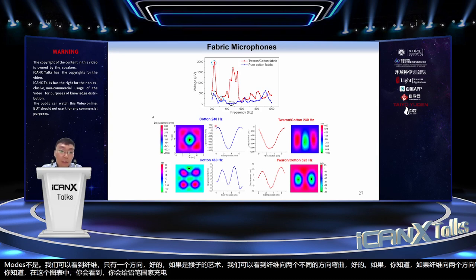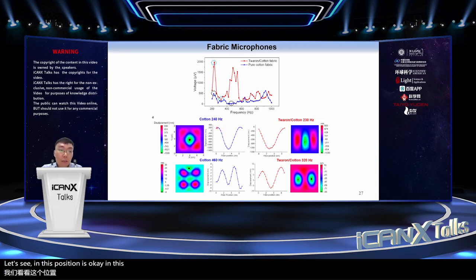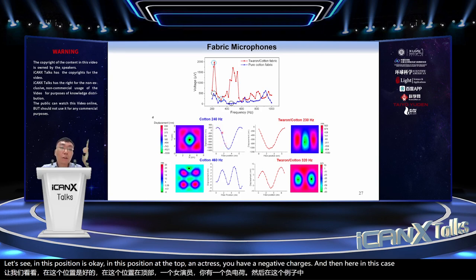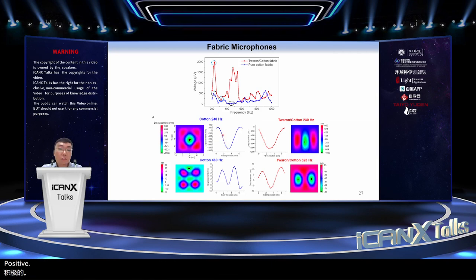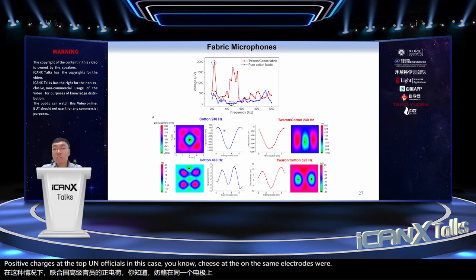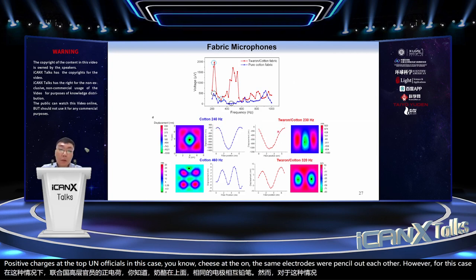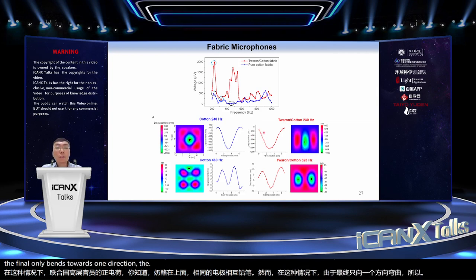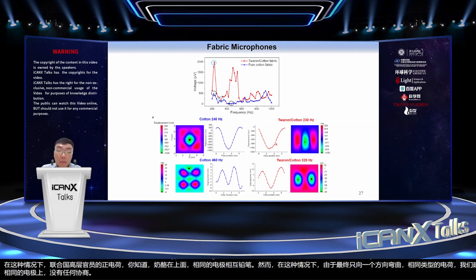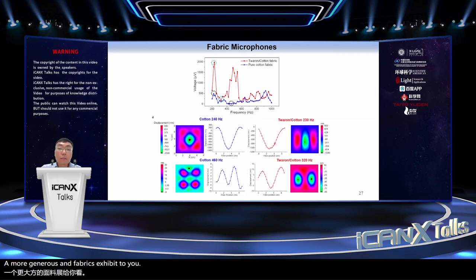And if the fiber bends towards two directions, you will see charge cancellation. Let's say in this position, at the top electrodes, you have negative charges, and then in this position you have positive charges at the top electrodes. In this case, charges on the same electrodes will cancel out each other. However, for this case, since the fiber only bends towards one direction, the same type of charge is built on the same electrodes without any cancellation. So this explains why the high modulus fabrics exhibit superior performance.